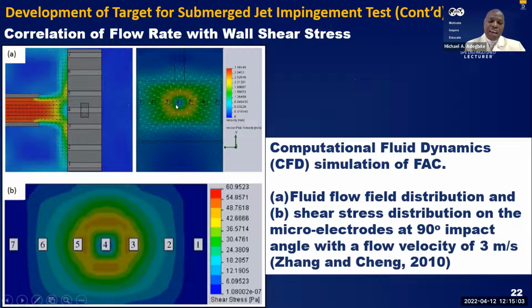within a radial distance of between 2 and 3, especially around 3, we have a radial distance that is associated with high flow, high shear stress, high turbulence in terms of flow regime, flow patterns. Of course, directly under the jet, let me spotlight that. Directly under the jet is a stagnant region. And the same could be noticed in this stagnant region. That's directly under the nozzle.